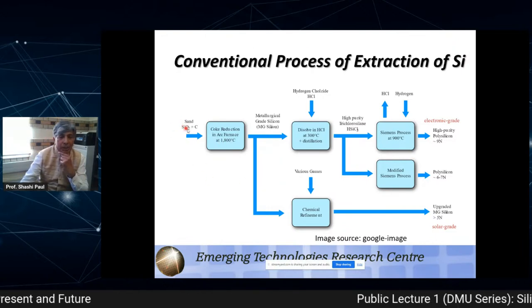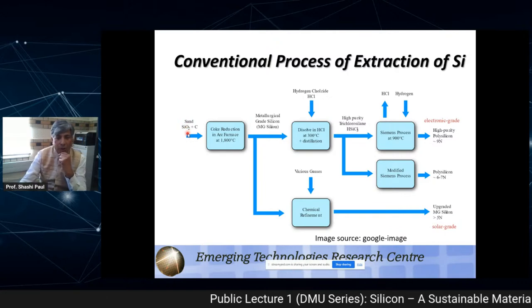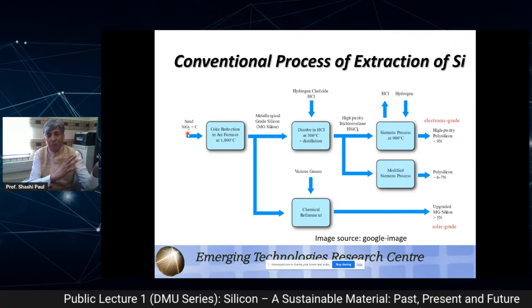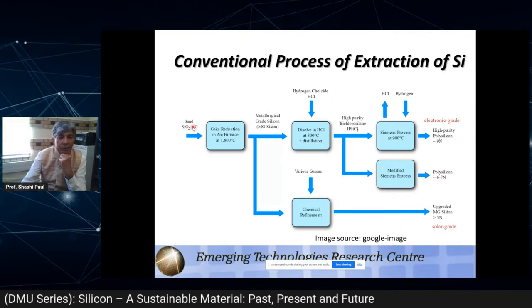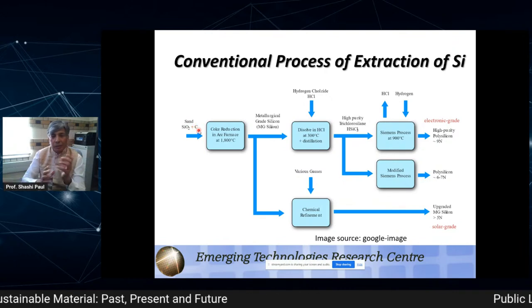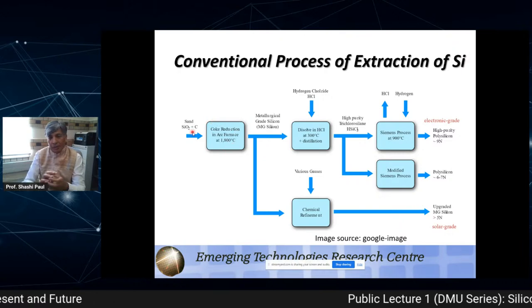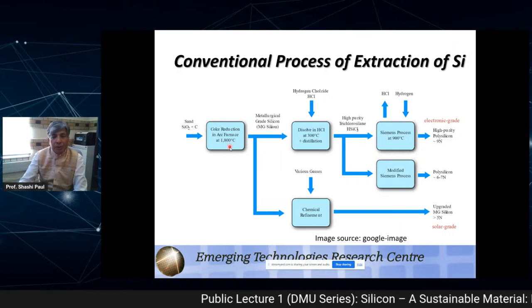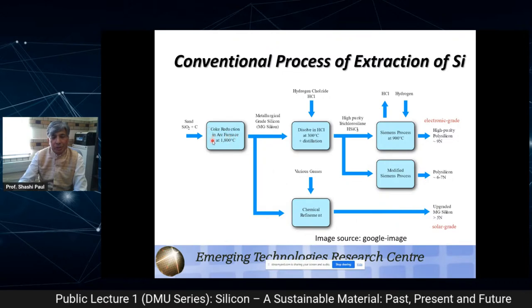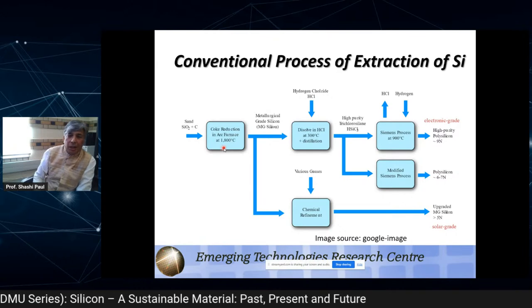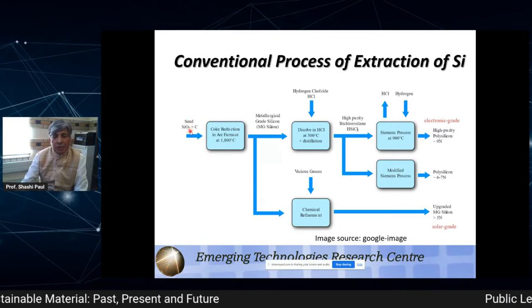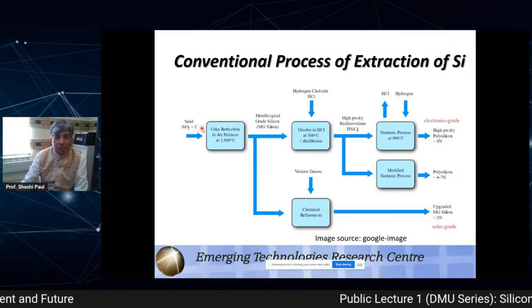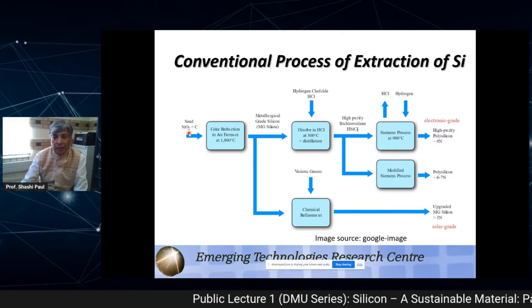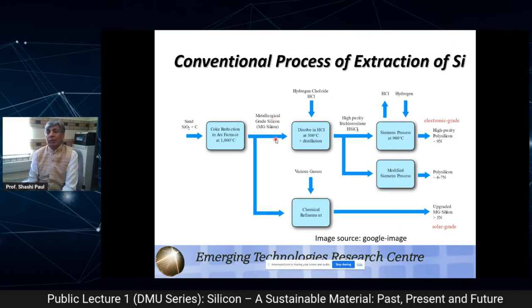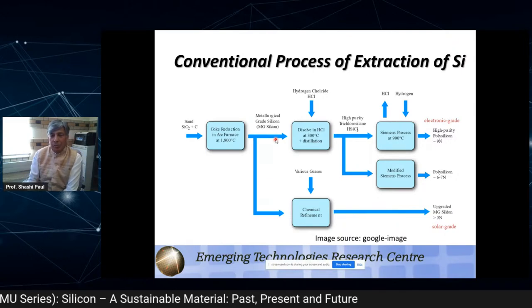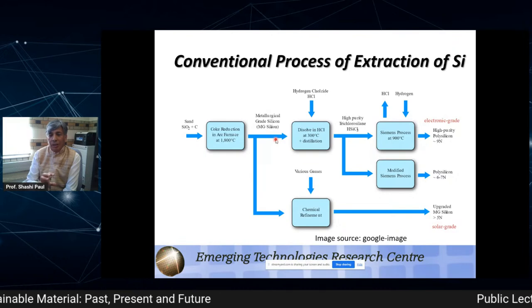So this is sand, which is silicon dioxide. It is washed, so you can take some of the impurities, not all, away, and then you add carbon, generally coke, and mix it up. Then you put it in a furnace and raise the temperature quite high, to 1800 degrees centigrade. What happens is a simple chemistry: the oxygen reacts with carbon and produces carbon dioxide, and you get metallurgical grade silicon.